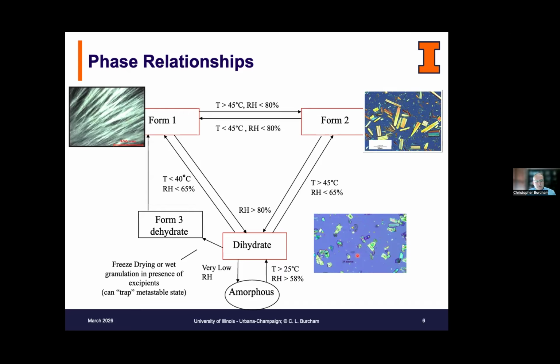And so everything seemed to be great until we put the material on stability, and we found that in the formulated tablet, the dihydrate dehydrated, and it resulted in a mixture of Form 1 and Form 2. Not acceptable from a solid state perspective to carry forward, and certainly not very controlled. So it didn't fit with the idea of a quality by design product. So we started to turn our attention to Form 2.